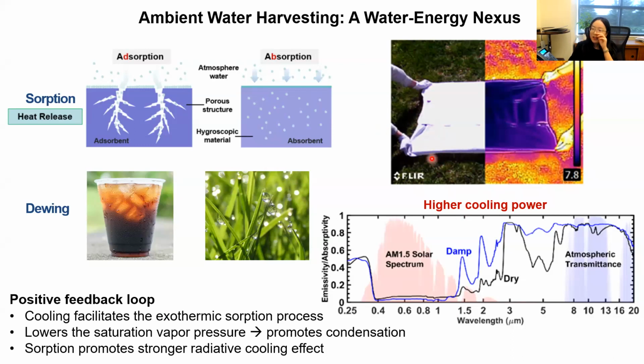This is an image of the group members holding several pieces of the fabric. As you can see, this is the photo image and this is the IR image. It features a much lower temperature compared with the ambient. And we're looking at the electromagnetic response here, where the material features a low absorptivity under the solar spectrum and a high emissivity in the mid-IR, especially from 8 to 13 micron.